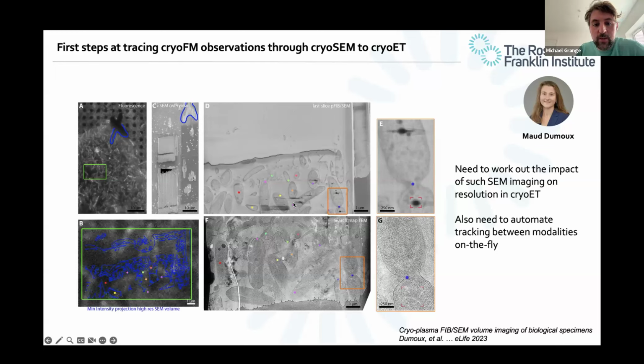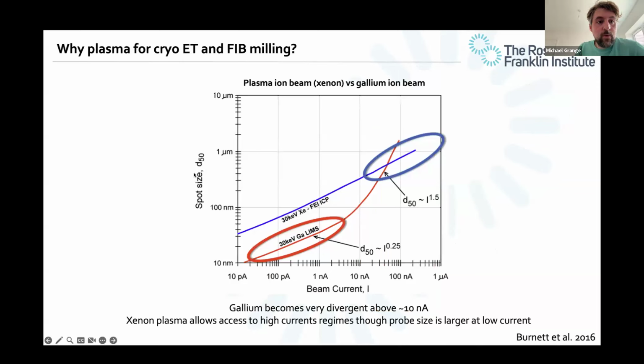And you might ask why these look quite different, the TEM overview and the SEM overview. And the answer is, well, with low kV and using a scanning electron microscope, you only penetrate 5 nanometers or so of the sample. And so the surface of this will look different to the projected image that you see in the panel below. So why plasma?